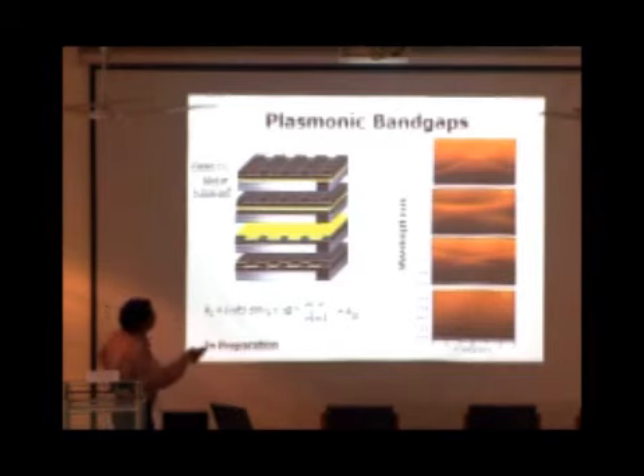So what we see in this structure is you have a band gap as expected, but the line width is much shorter, showing that the lifetimes could be much longer.